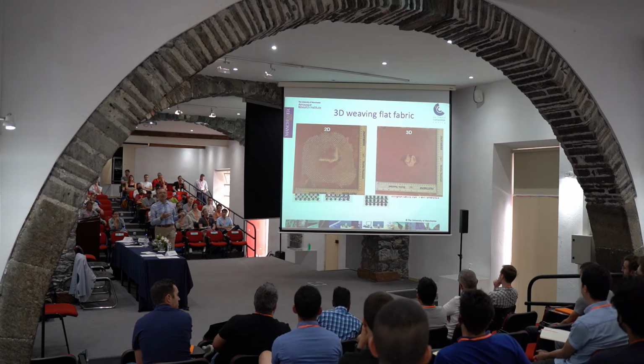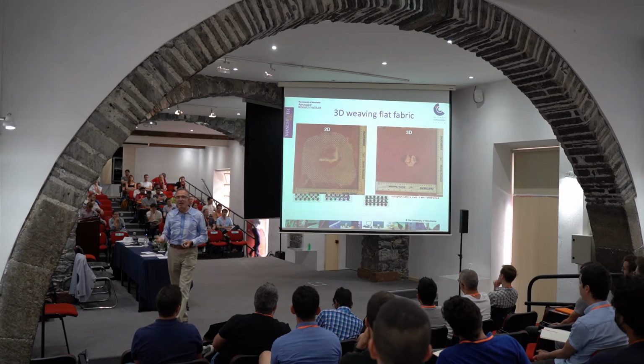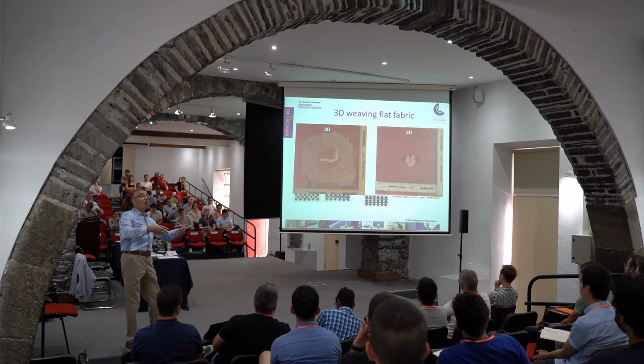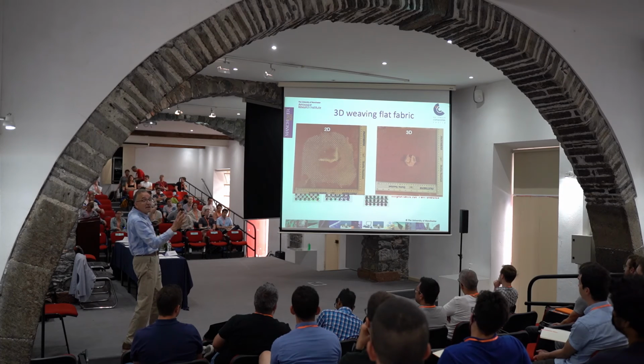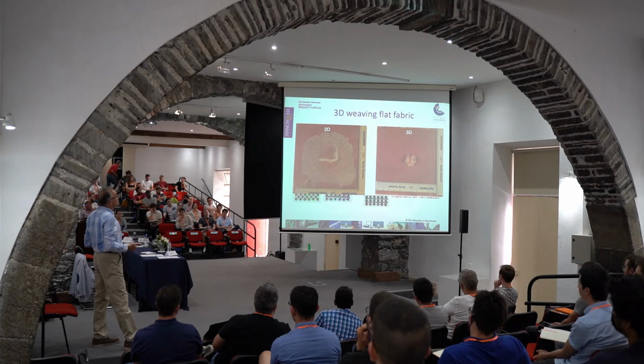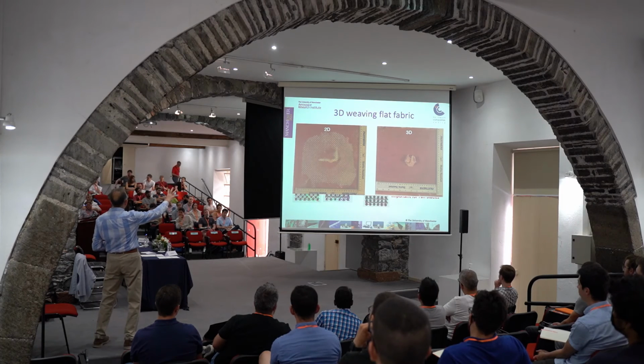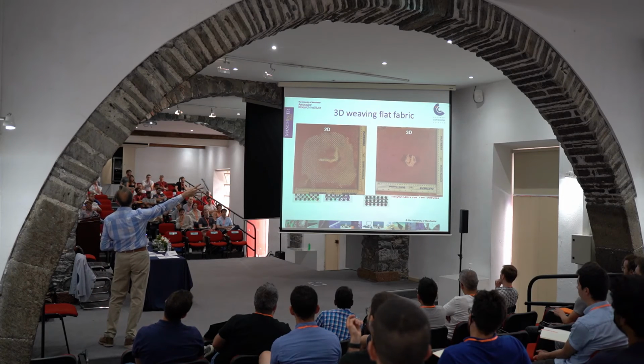And here we compare a two-dimensional woven fiber laminate with a three-dimensional fiber architecture undergoing some kind of impact loading. And yes, both of them get fiber break, which is unavoidable because you have exceeded those critical values. But the 2D experiences extensive delamination in comparison to the 3D, which is reinforced with through-thickness fibers.